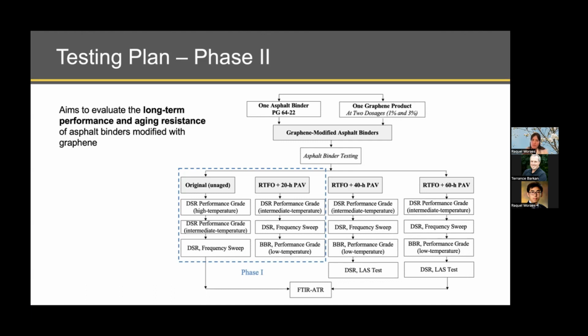So with that in mind, from the results that we obtained in phase 1, we saw that we could go up to 3%. So we estimated using 2 dosages in phase 2 for further evaluation, to see also whether in a higher dosage or in a lower dosage, when considering long-term aging, the agglomeration property or segregation property of these products could be captured. And with that, I finish my slides today, and I'll now give the opportunity to Fan to give his input on our results.